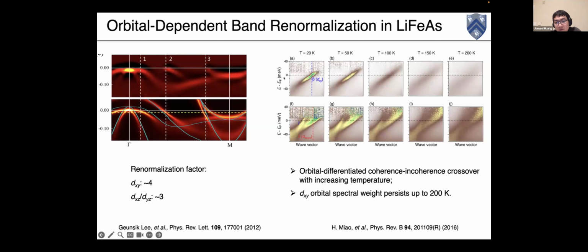The temperature dependence experiments also show that this orbital differentiates the coherence-incoherence crossover. They did the experiment up to 200 Kelvin. Up to 200 Kelvin, they still say the orbital retains a finite spectral weight. So there's no real orbital selective Mott transition with increasing temperature.